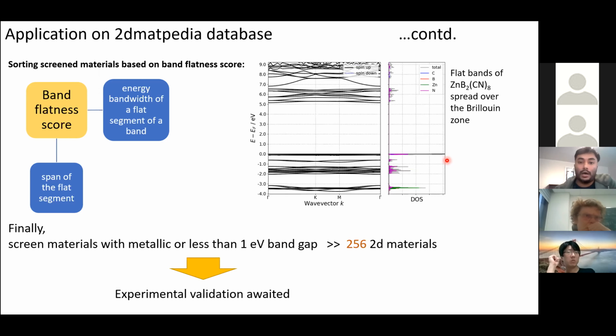So based on that, we sorted the list of 700 materials, and near the top we get materials like this, which have very flat bands near the Fermi energy, spread throughout the Brillouin zone. Now this material has a very high band gap. In many optical and electronics applications, it may be more beneficial to have materials with smaller band gaps or metallic materials. So we further filtered out materials which have less than 1 eV band gap, and we're left with 256 materials. These 256 materials are now a good starting point to work manually on each of them and to look for interesting materials.